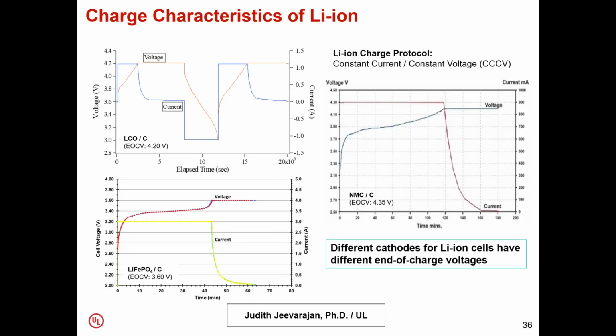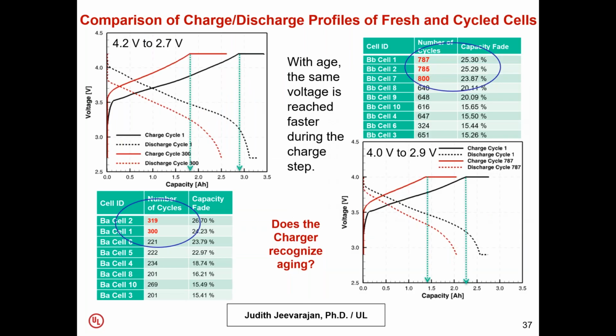And the reason I was talking about the charge protocol is because, as I mentioned earlier, depending on the cathode chemistry, and here I've only shown the cathode chemistry, this can change with anode chemistry too. You can see that a cell can be charged to 4.2 volts if it's a lithium cobalt oxide, or 4.35 volts if it's a lithium NMC cathode, or to 3.6 volts if it's an iron phosphate cathode. So the charger should be able to recognize the chemistry.